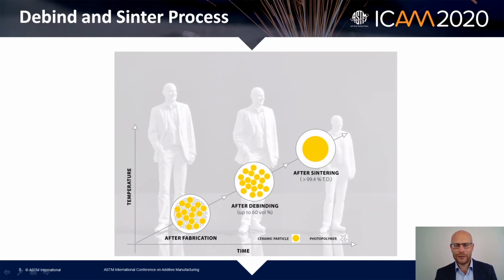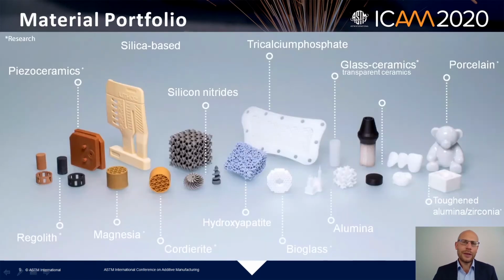It will be transferred into the furnace where we have then the debinding, which means the UV curable binder is burnt off, and then we have the sintering where the parts shrink together and achieve the resulting mechanical properties or the resulting densities and strength. This is nothing special for the 3D printing approach. This is basically what every ceramic part has to go through, and therefore the ceramicists are well aware of this technology.